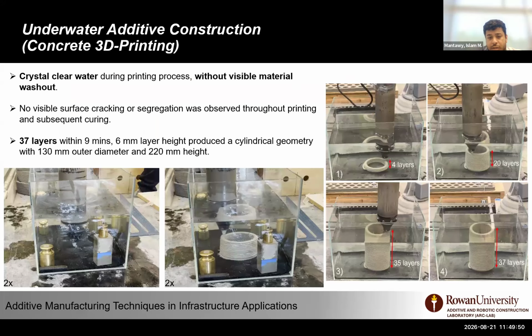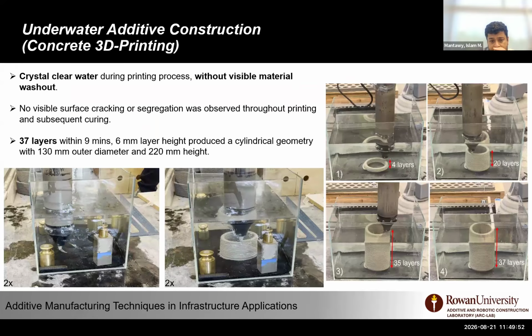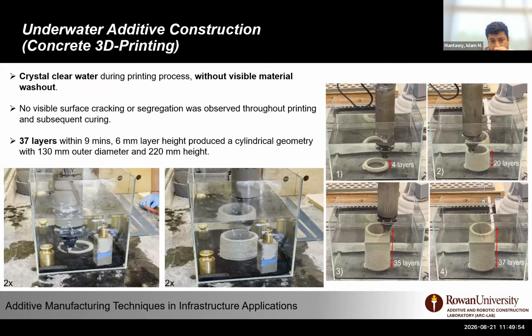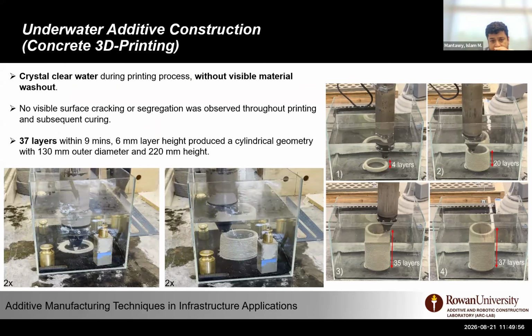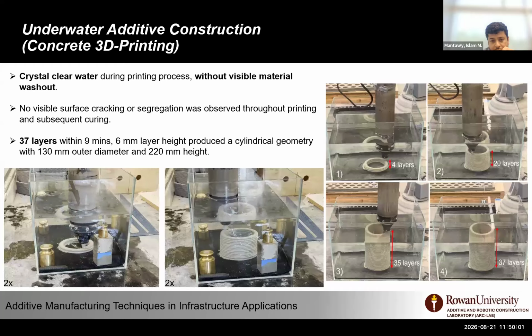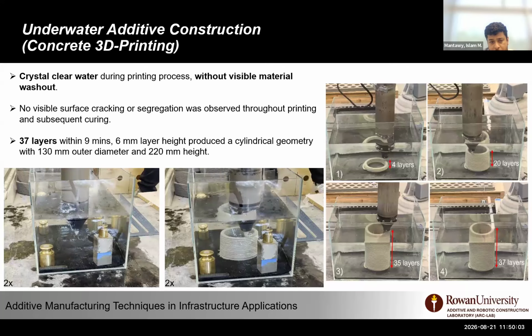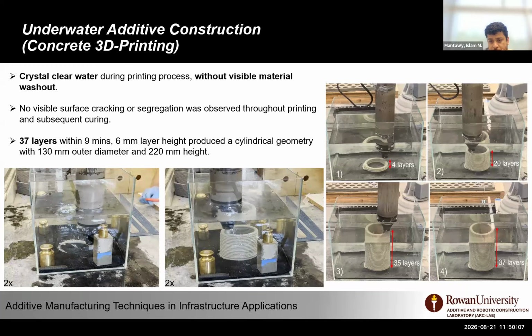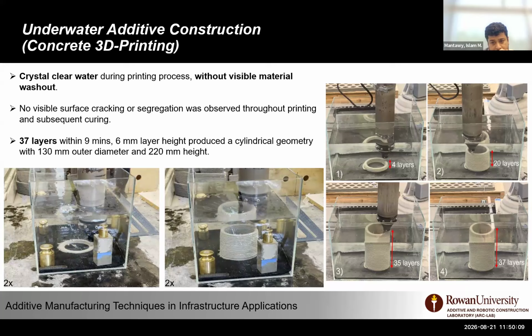So as you can see here, the material is actually printed as a few cylinders underwater. I know it's not large scale. We are using the tube, but we are also trying to scale that up using the auger system. And you can see here we achieved almost 37 layers without noticeable washout.